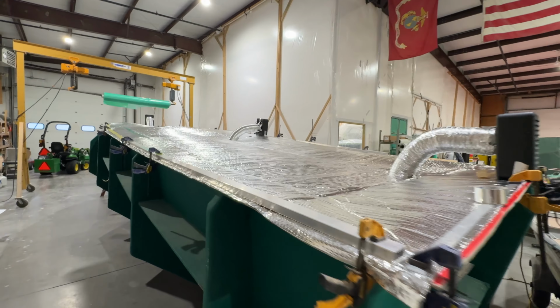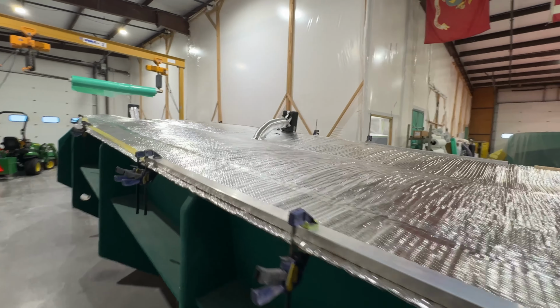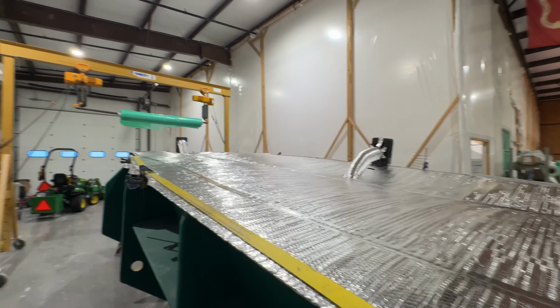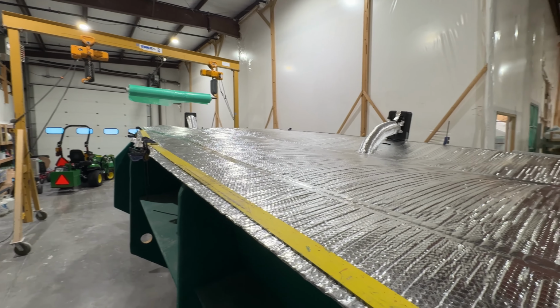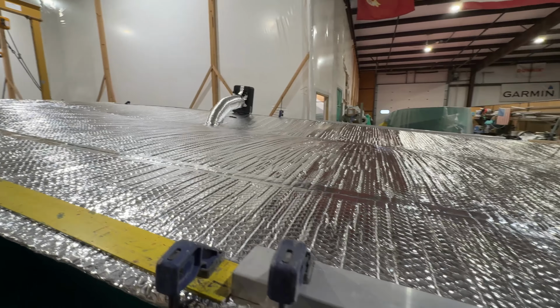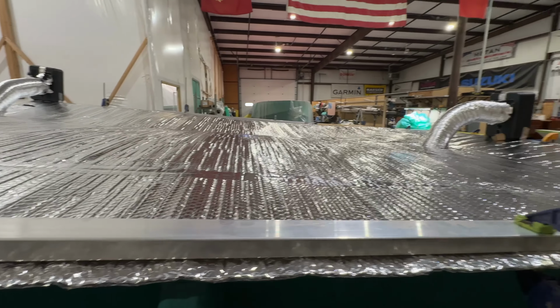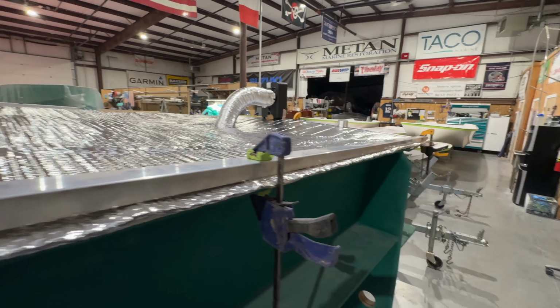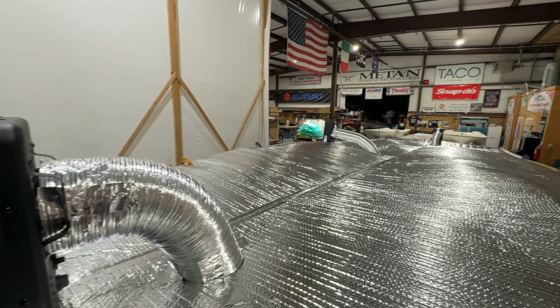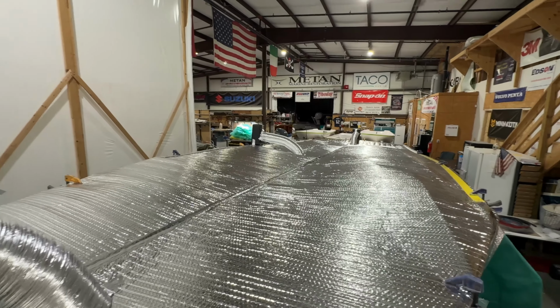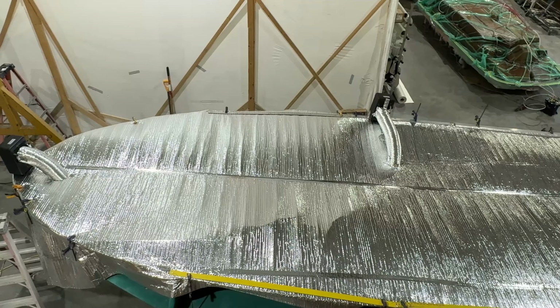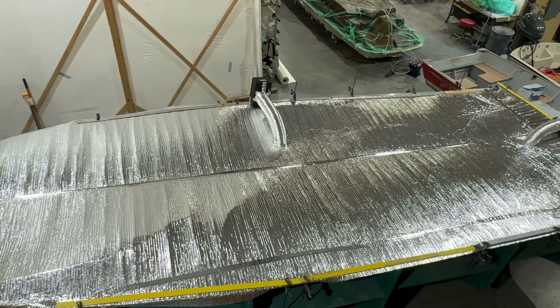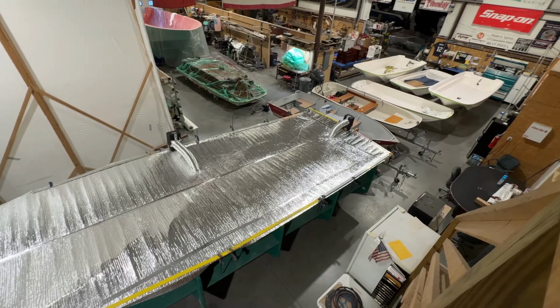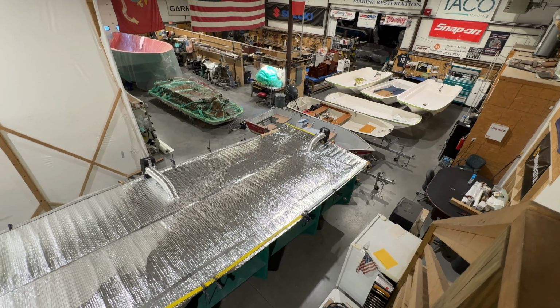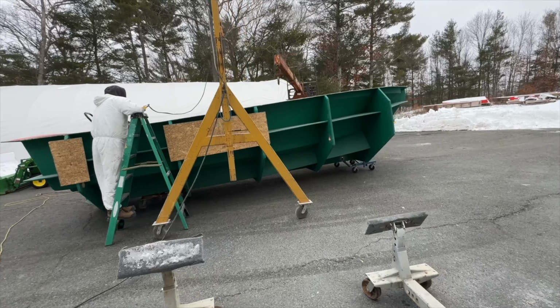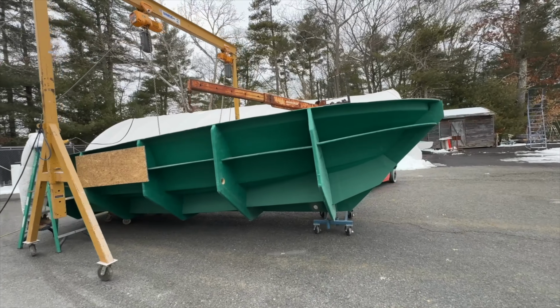After the initial 24 to 36 hour cure time following the injection of the stringers to the 26 Barretto Cove, we're now going through a 12 to 14 hour post-cure process where we are bringing the temperature up to 120, 130 degrees. We'll then slowly ramp it down, bringing it back down to room temperature. At that point, the layup will be post-cured, adding significant strength to the molecular makeup of the epoxy resin. When this comes out of the mold, you're all going to be in for a bit of a surprise.